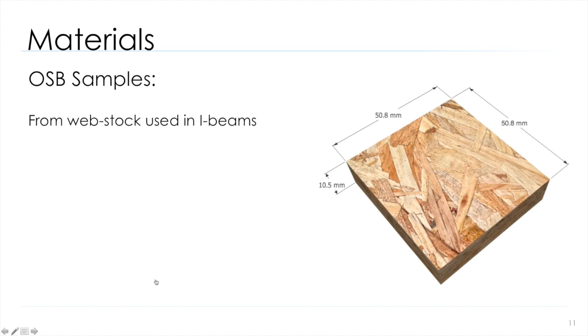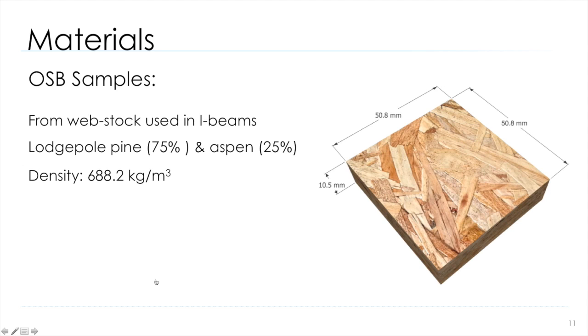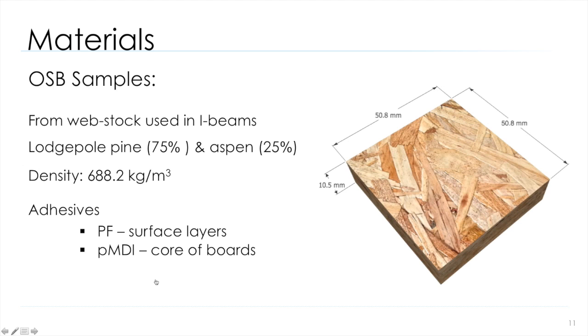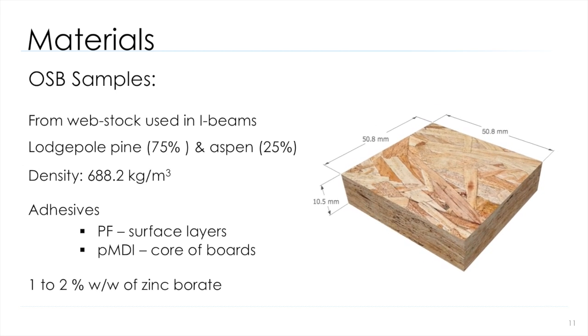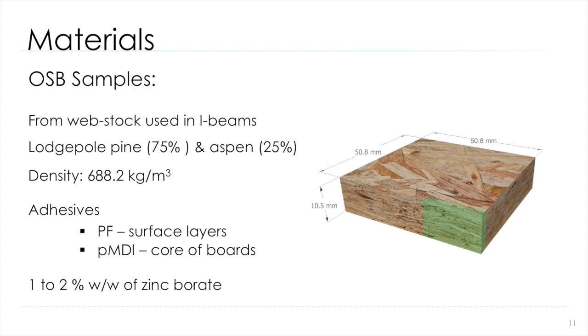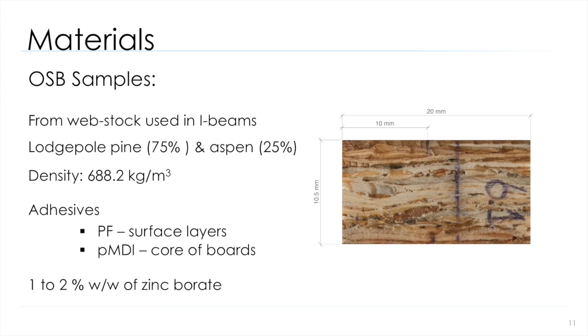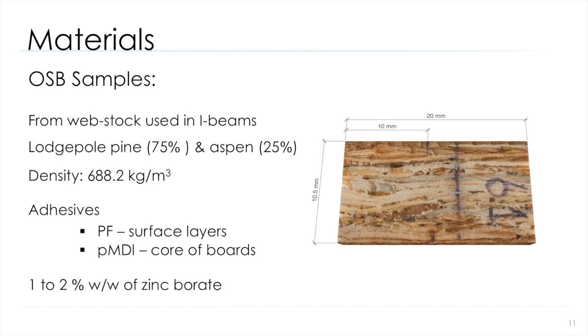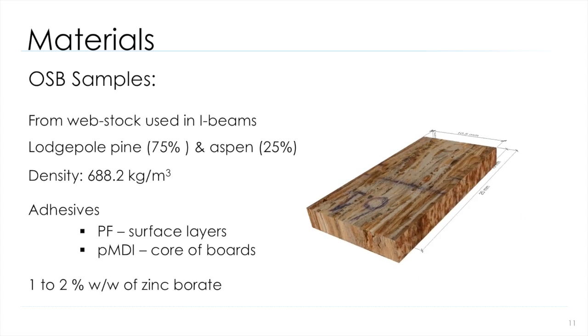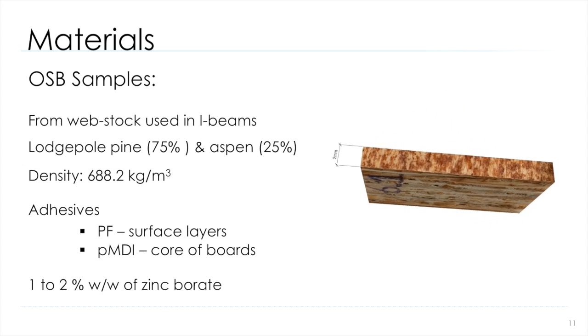So the material we used to carry out this study is OSB used in I-beams, and it's made from a mix of lodgepole pine and aspen. The density of this material is around 700 kilograms per cubic meter. The adhesives used in this OSB are phenol formaldehyde and PMDI, and it contained zinc borate. Initially we obtained samples measuring approximately 50 by 50 millimeters and 10.5 millimeters of original thickness of the board. From those samples we extracted specimens measuring 20 millimeters long by 10.5 millimeters, which is the original thickness as I said, and a width of 2 millimeters.